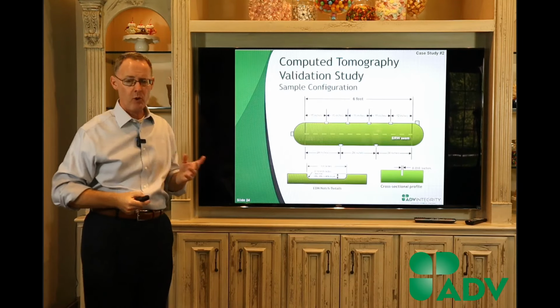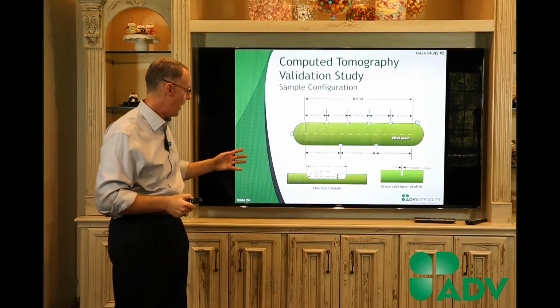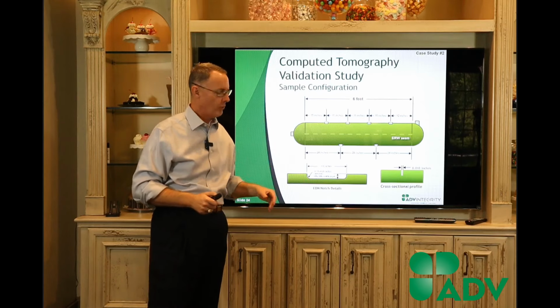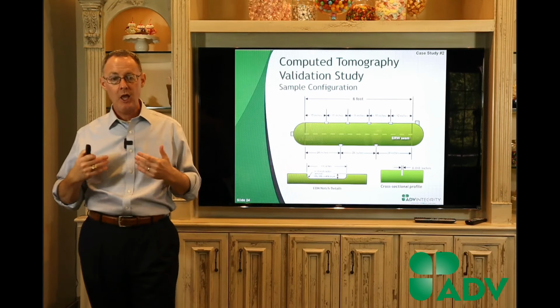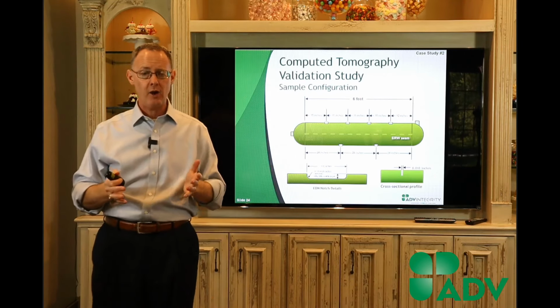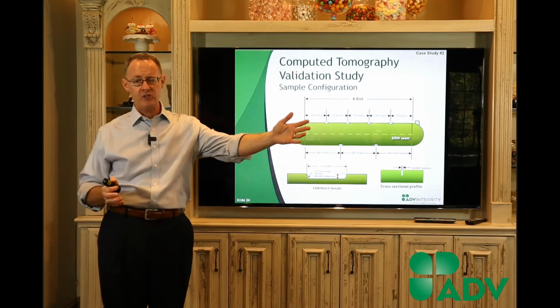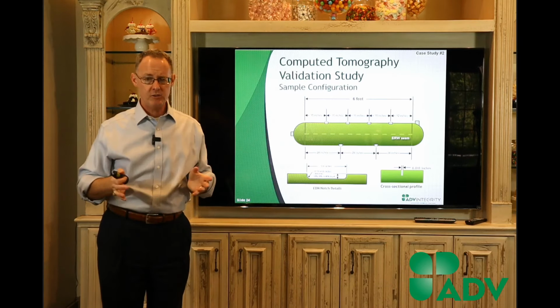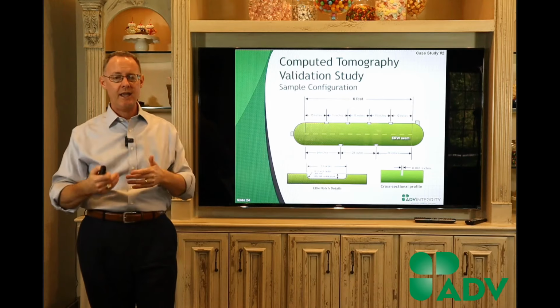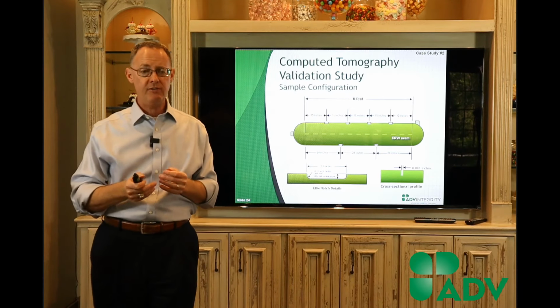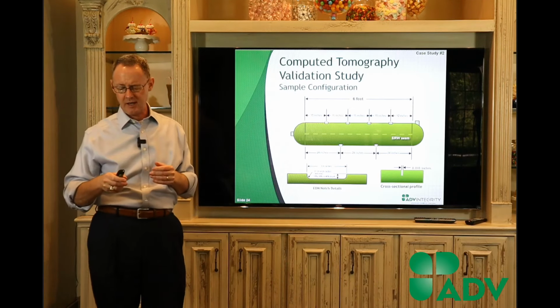And so we did a little project for him. We took some 12-inch pipe, we put some EDM notches ranging from 10 to 40%. We did some pressure cycling to create cracking, and then we sent it back over to James and we let him make some inspections, and then we got his data back and we broke all of these features open, and we did kind of a side-by-side comparison.